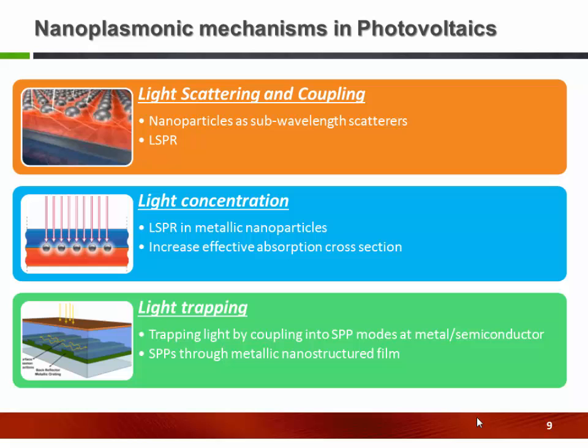the absorption rate. One other technique is coupling the light to the local surface plasmon resonance, so that we increase the concentration of the light locally inside of the absorber layer. When we increase the concentration or density of the light, we can increase the absorption at the same time. The other technique is coupling the light to some sort of surface plasmon polariton mode.